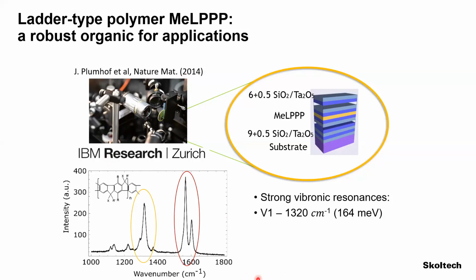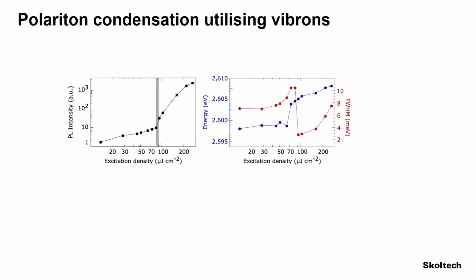So at that point, I wanted to see if we can apply the studies that we have done in J aggregates and inorganic semiconductors, utilizing phonons to dissipate energy, to do the same thing with this kind of very stiff molecules. And by doing that, what we observed is that actually we can lower the condensation threshold. So here you can see the photoluminescence intensity as a function of the excitation density where you hit threshold. So you have a nonlinearity. That is the point where you form the polariton laser, the ground state polariton condensate.